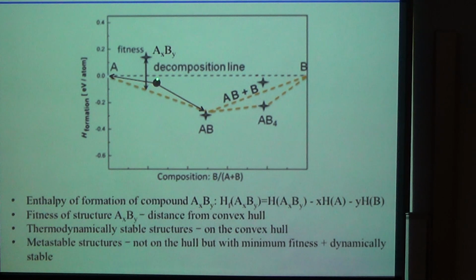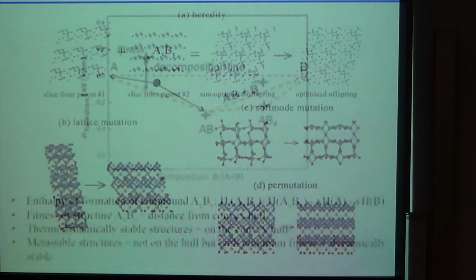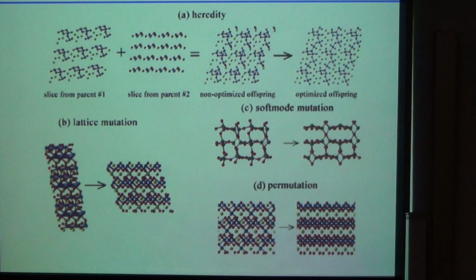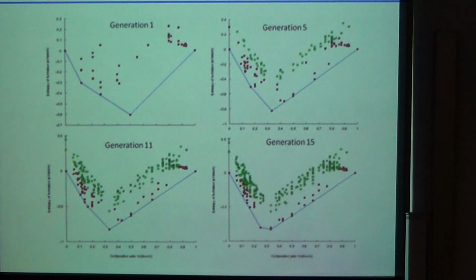So although this point is not thermodynamically stable, it might be metastable. Metastable means that it's locked into a local potential energy minimum. And we check whether it's a potential energy minimum by calculating the phonon spectrum. So these are just the illustration of the variation operators. We take two parent structures, slice them, and mix them together, showing heredity. So we have lattice mutation, soft mode mutation, permutation. This is the technology, so I don't want to go into the technology. But this is how this convex hull all works.